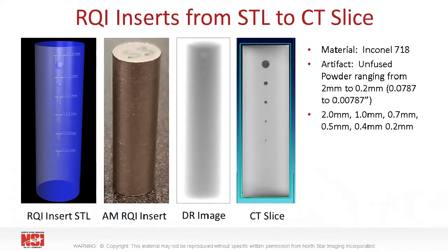This slide displays the STL dimensions of the RQI insert for the spherical unfused powder defects. The sizes range from 2 mm down to 0.2 mm. The 5 larger indications are clearly visible in the image, but the 0.2 mm indication is only visible with further digital magnification and contrast enhancement.